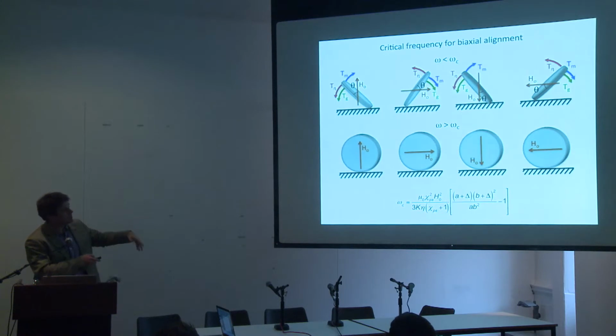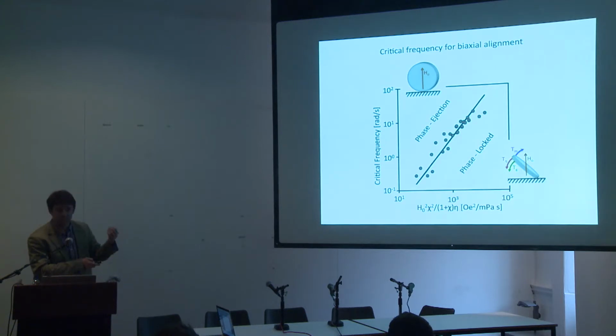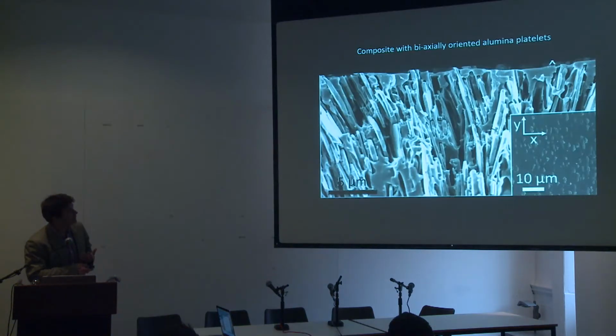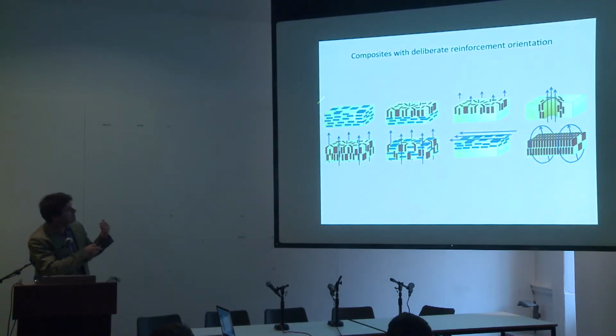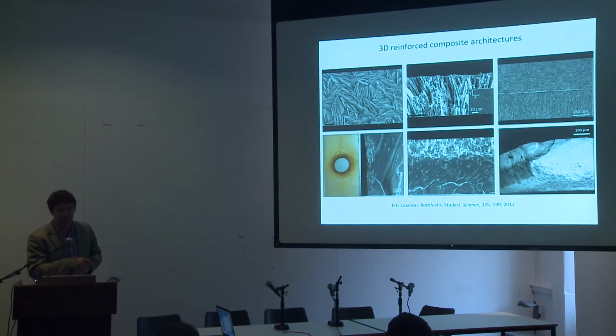So you can model all this and come up with an expression that tells you what the velocity of the rotating field needs to be in order to achieve this alignment. I won't go into the details here, but that's a very important quantification needed for the actual realization of the alignment. And here's an example of an unusual orientation, an out-of-plane orientation that you would not get by, for example, just applying shear to the system, that we are able to achieve using this technology. And you can imagine many other possibilities using the rotating field, static field, field gradients, combinations of responsive with non-responsive platelets, and so on. And here are some real microstructures that we've been able to realize using this approach.